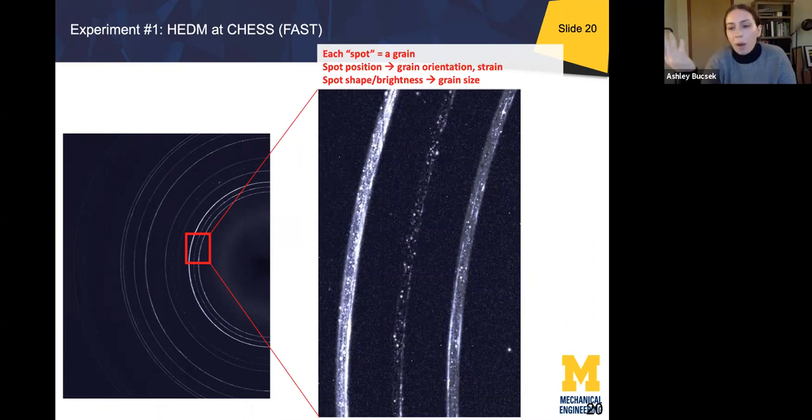And our hypothesis is that maybe the cleaner of those grains are the ones that are sticking around, and they're basically jumping the gun on those annealing processes. There's not as big of an energetic driver for recrystallization in those grains because they're cleaner from being dynamically recrystallized. That's sort of our hypothesis.